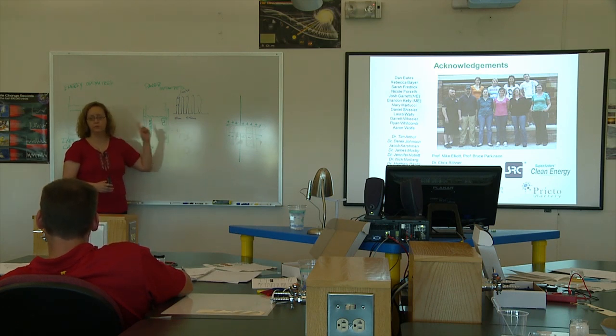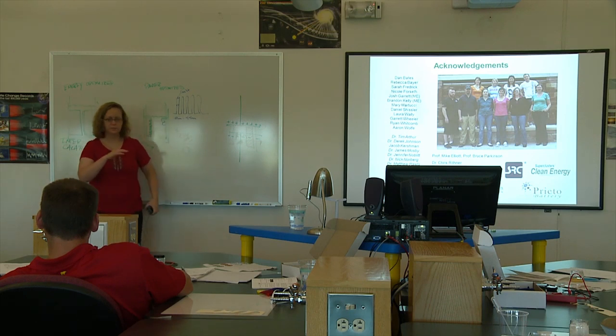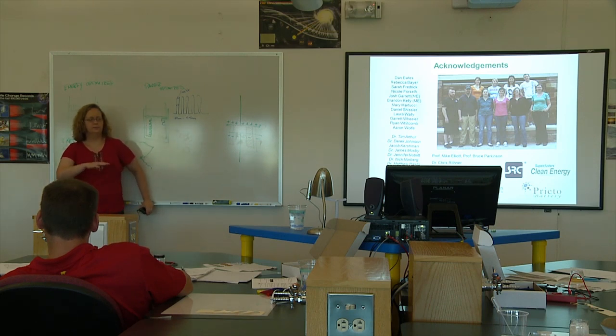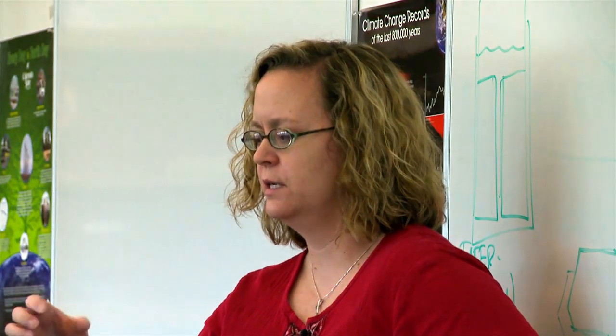We grow it ourselves. And the way we do it is we start with a piece of aluminum metal. And if you oxidize it in an acidic solution, it's called anodization, you grow this amazing structure that is holes that grow straight down. They don't ever intersect. And you control the diameter of them and their spacing. It's very similar to what they do for aluminum siding on a house. They put this thin aluminum oxide layer to make it really stable, particularly to rain. It's the same exact idea, except we grow it so that these holes grow in a certain way.